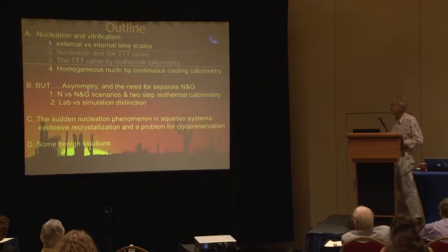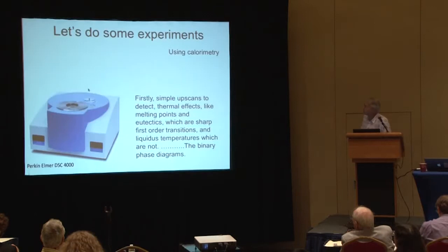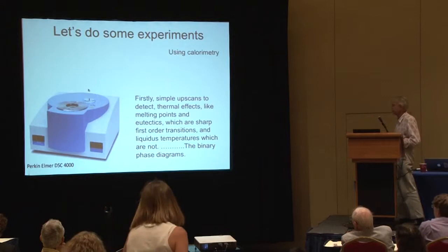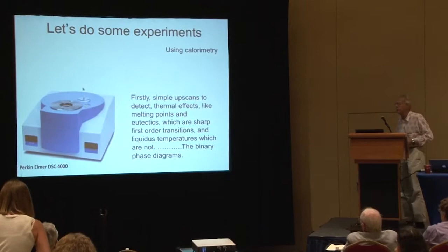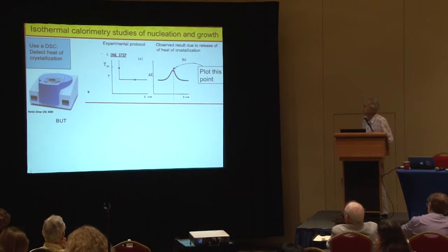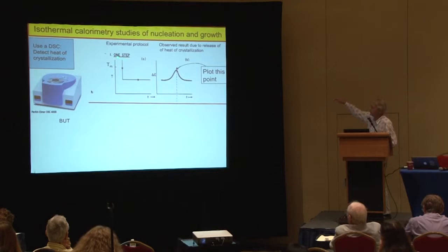Bringing us to the subject of experiments on this. So here's a differential scanning calorimeter, and we're going to look at the determination of the time at which a crystallization event begins, by putting a sample in and following this protocol, which I call the one-step isothermal calorimetry protocol.